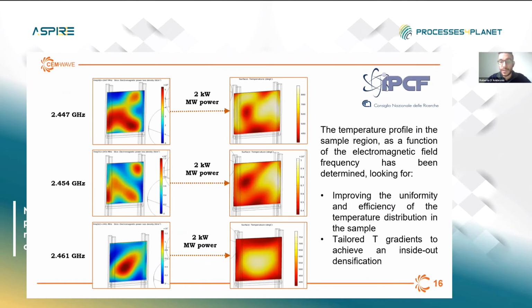The main outcome of the modeling will be, of course, the temperature profile in the sample region as a function of the electromagnetic field frequency, which has been determined looking for two main targets, which were the improvement of the heating uniformity to favor a wider densification of the material, and secondly, the tailoring of the necessary temperature gradients to achieve the characteristic inside-out densification of our CMCs.